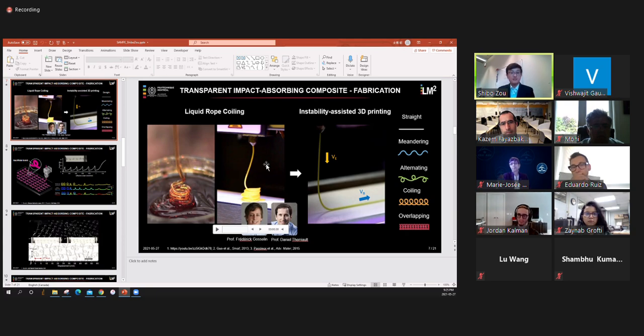So we use that FDM machine actually to try to create this similar pattern, coiling pattern. But actually, it was more complicated than we thought, because here, in order to take advantage of this instability of this molten polymer, we have to have high viscosity. I mean, we have to have the viscous behavior of the material. So we have to use high temperature so it can coil on itself. But there's a problem if we use a continuous fiber extrusion system. That is, when the material is in the viscous behavior with a high temperature, the polymer will flow, and the fiber inside will try to expand, and this actually makes the instability disappear. So it more acts as an elastic body. So we tried this, and we couldn't get a very good instability deposition behavior.